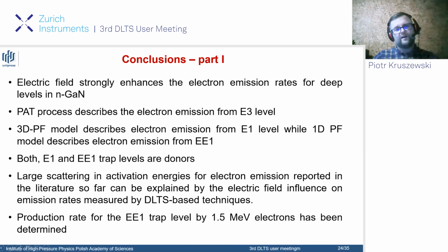Both traps, E1 and EE1, are donors, and the large scatter in activation energies reported in the literature can be explained by the influence of the electric field.